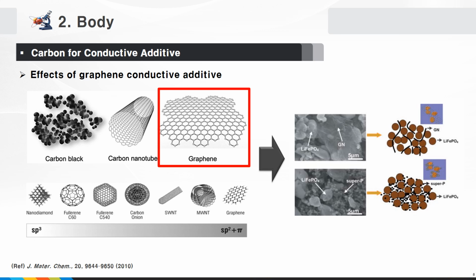Conductive materials are used only in a small amount in the electrodes, but they play a very important role in improving the performance of an LIB. A variety of sp2 carbon materials such as carbon black, conductive graphite, acetylene black, and carbon nanotubes have been used as conductive materials. In particular, graphene has a 2D structure compared to commercial carbon-based conductive materials with point-to-point conductive mode, so it can form a flexible conductive network through the point-to-plane mode and connect active material particles more effectively with a much smaller amount.